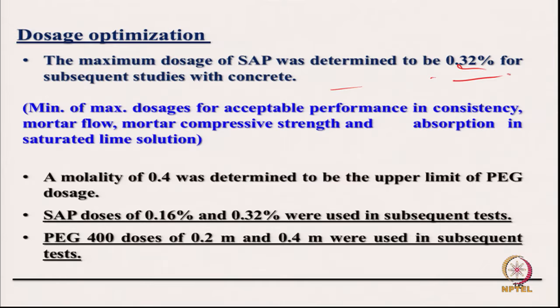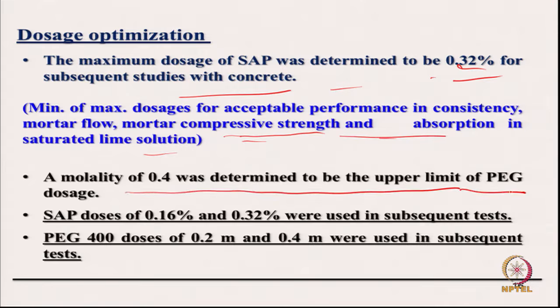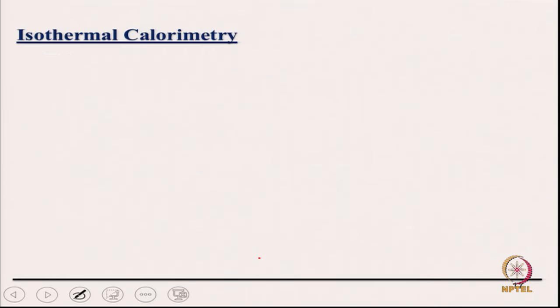The maximum dosage of SAP could be of the order of 0.32%, so you can optimize them and find out what is the best. Find out the minimum and maximum doses of acceptable performance in consistency, mortar, etc. A molality of 0.4 was the upper limit of PEG concentration we are talking of. SAP doses of 0.16 were used. So, some more results are available.